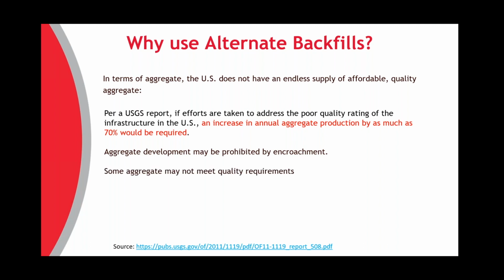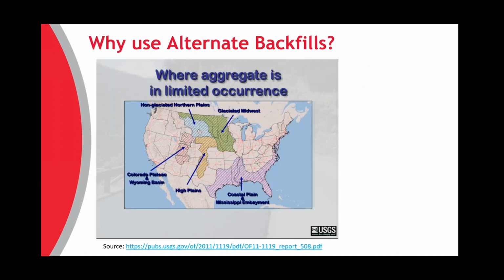Some aggregates don't meet the quality requirements, such as the electrochemical requirements that are put forth. Also, aggregate is pretty widespread, but it doesn't occur everywhere in the United States. This is a map, again, by the USGS that indicates areas of the country where you have limited occurrence of aggregates. And you notice these are along the Gulf Coast, up the Atlantic coast, and pretty much in the upper Midwest area. So what does this mean? Well, haul distances obviously increase the cost of your backfill materials. It's estimated that haul distances of 30 to 50 miles can double the cost of aggregates.